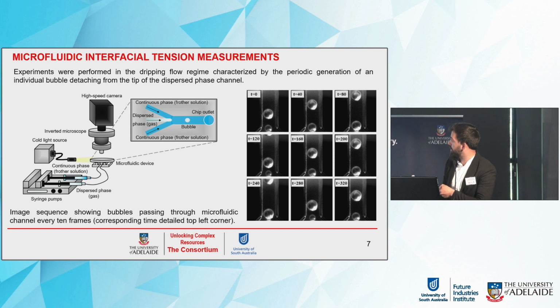And here is our design of the microfluidic chip, where we have a dispersed phase channel in the center where there is an air pump. And we have two side channels that meet this one channel where we introduce our continuous phase, which is actually the frother solution. And these channels merge together to form one main channel where we observe our bubbles. And within this geometry, the size of the bubble is only affected by the continuous phase flow rate and the interfacial tension. And why is this important?